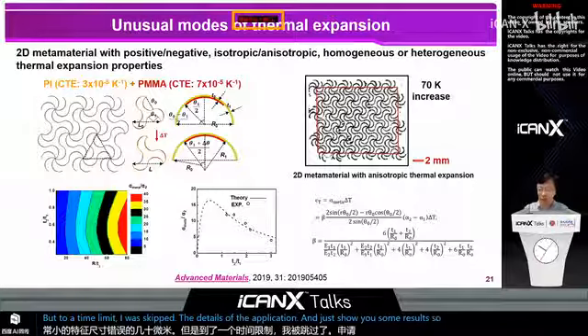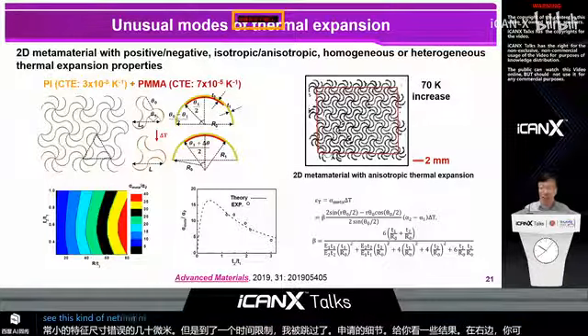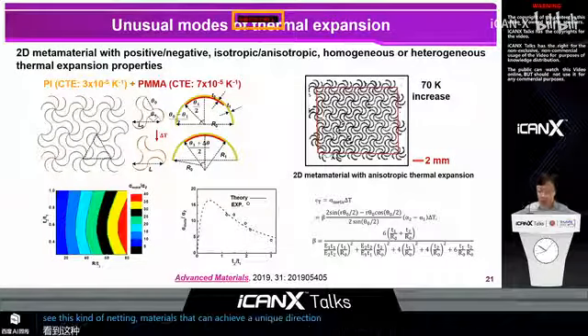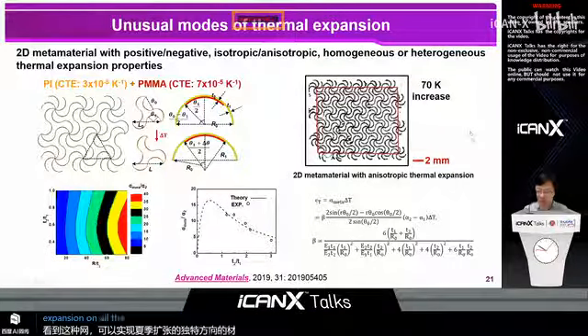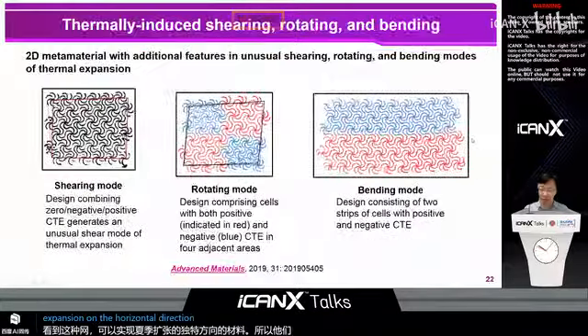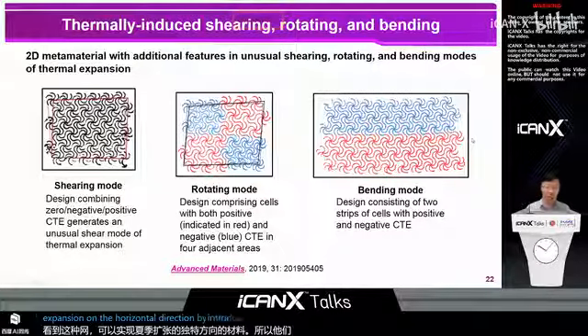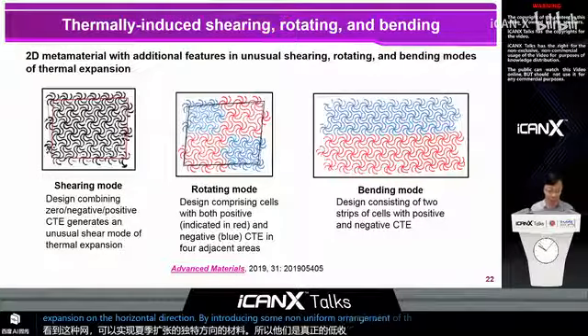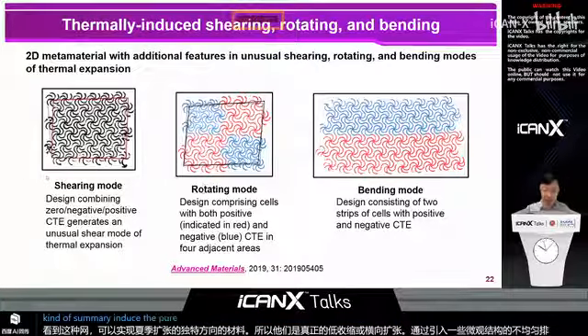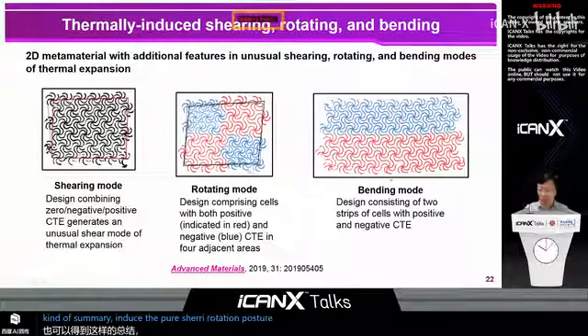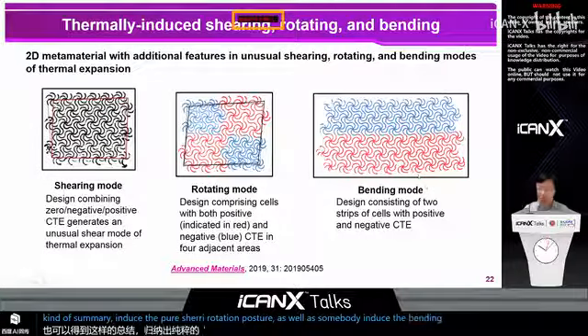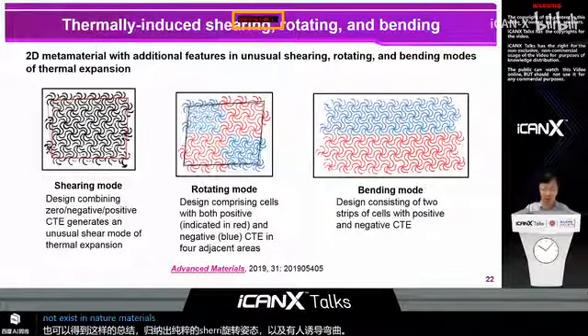So on the right, you can see this kind of metamaterial that can achieve a unidirectional thermal expansion. So there is low shrinkage or expansion along the horizontal direction. By introducing some non-uniform arrangement of the microstructures, we can also achieve this kind of thermally induced pure shearing, rotation plus shearing, as well as thermally induced bending. And most of these behaviors do not exist in natural materials as well.